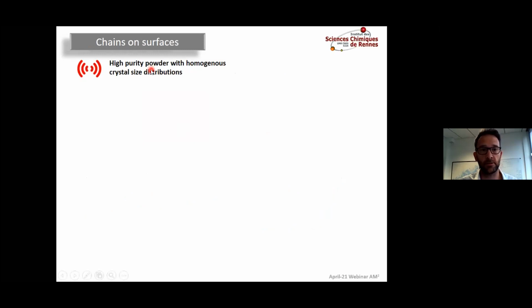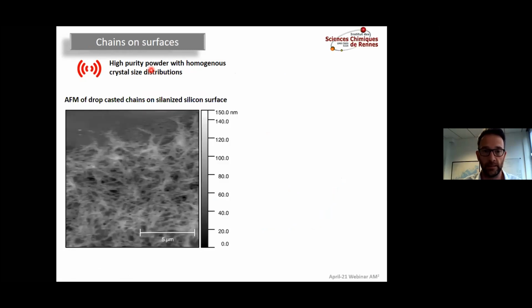Obviously, we are now sonicating everything, to have a high purity powder with a homogeneous crystal size distribution. And this is what we can see on silanized surfaces. We see nicely fibers. And here, for example, an isolated fiber that is pointing here.